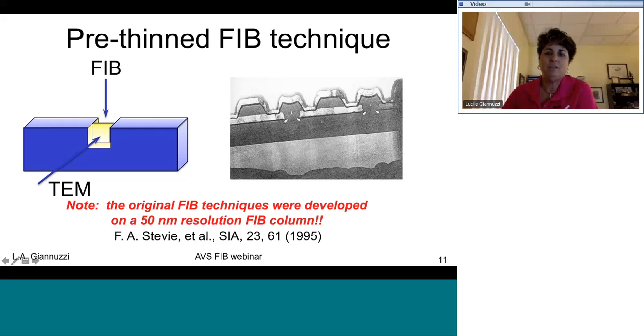But with 30 kV gallium FIB, it is often just perfect enough to do some very simple Fourier analysis and identify different phases. You can see bright field TEM material contrast very easily. And note again that this was done on basically a 50 nanometer resolution FIB column. So you can make these samples pretty easily.